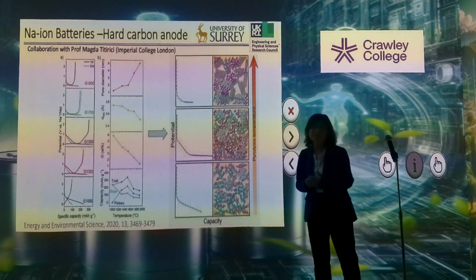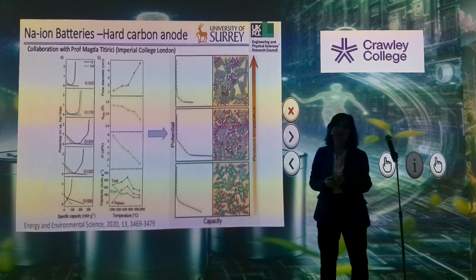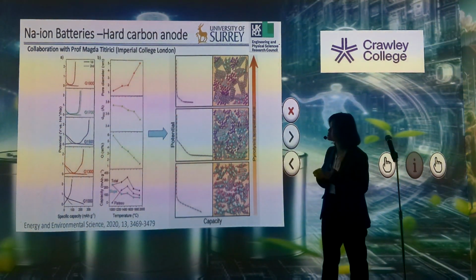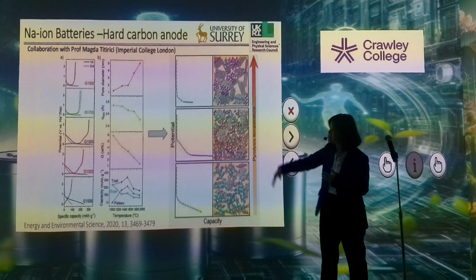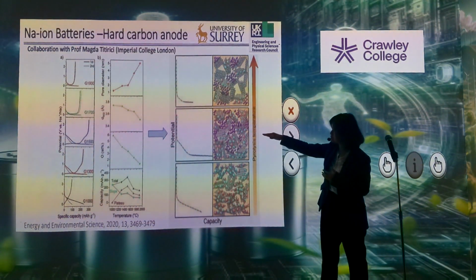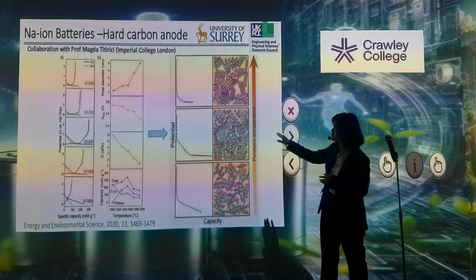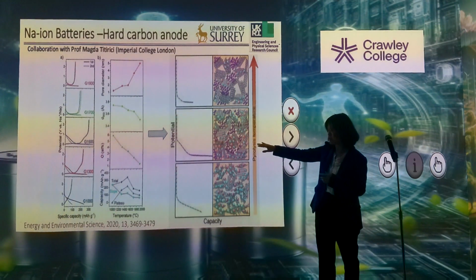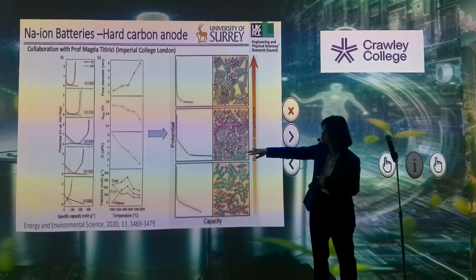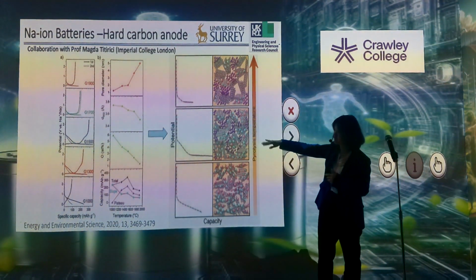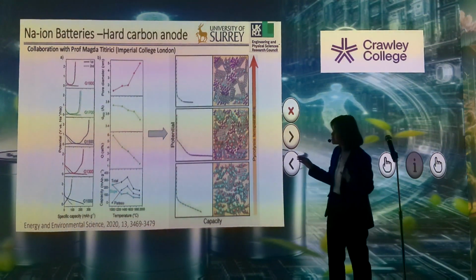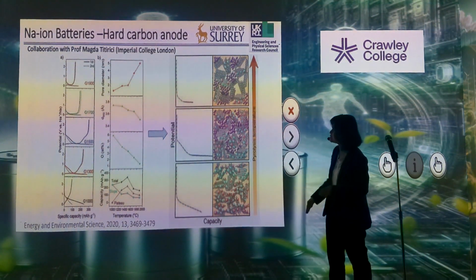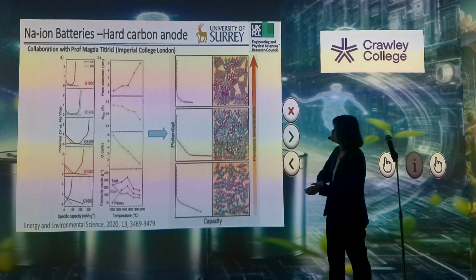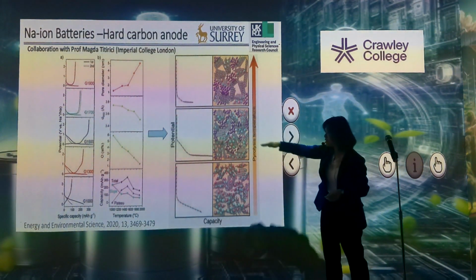So we then collaborated with a group at Imperial College London, and we suggested some structural properties to them. They made the hard carbon from biomass, glucose, and carbonized it at different temperatures, and found that the one carbonized at 1,500 degrees C gives the best storage capacity because it has a limited amount of oxygen defects and also a good interlayer distance. And then we propose this mechanism: we need a certain amount of oxygen defect to improve the storage capacity, but at the same time we need a suitable interlayer distance and pore size in order to increase the storage capacity.